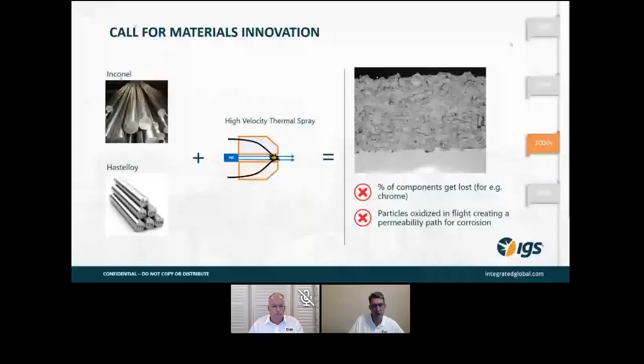What you see on your screen is a micrograph on the right. It's basically a cross section of the thermal spray coating that's applied. In this case, it's an Inconel 625. The light gray part at the bottom is the substrate material, for example a boiler tube or the inside of a reactor vessel. The coating is that mottled light gray and dark gray area. Just to give you a sense of scale, that's approximately 0.5 millimeter thick, so around 500 microns thick, or 20 mils if you're in the US. And the black above the coating just indicates the top of the coating.